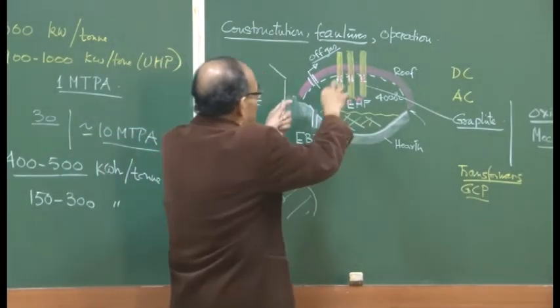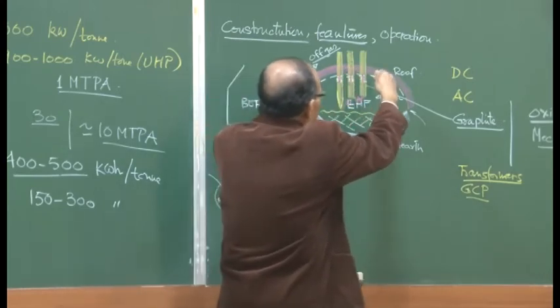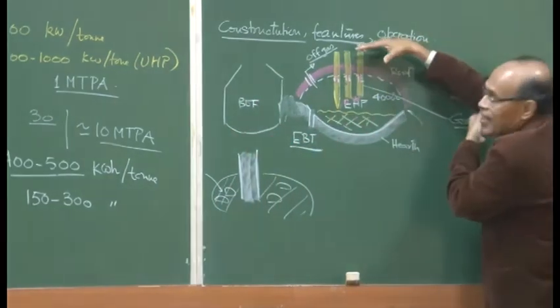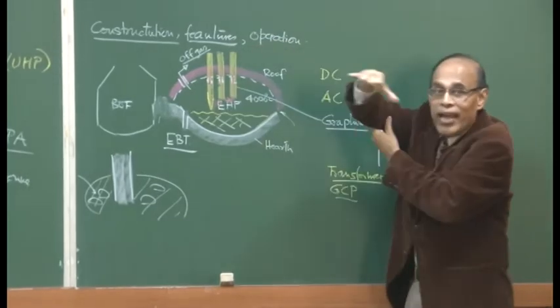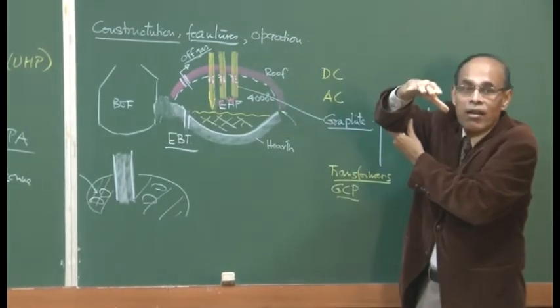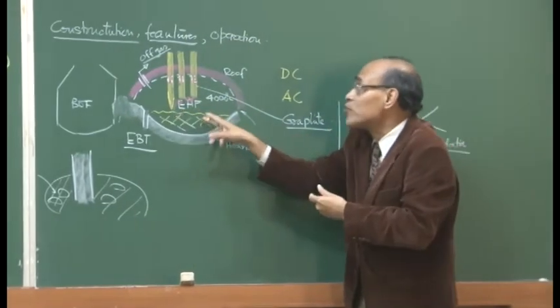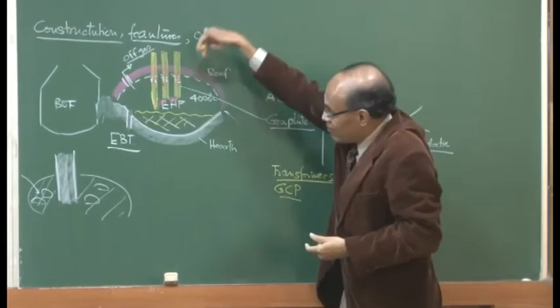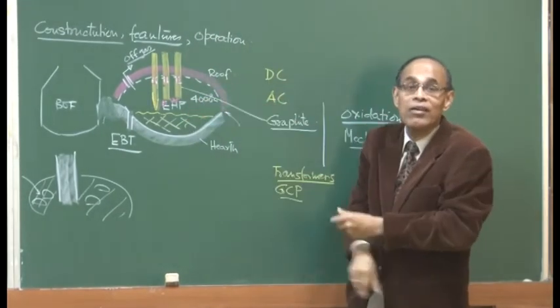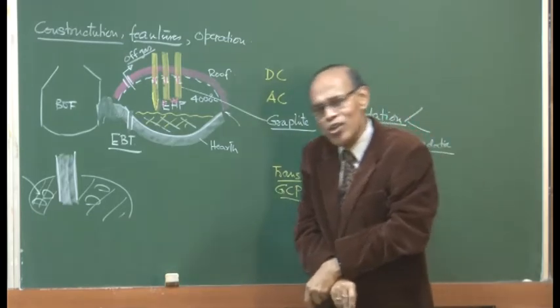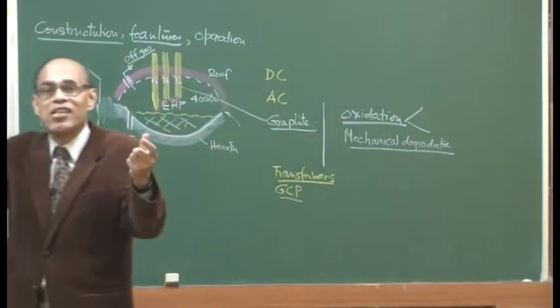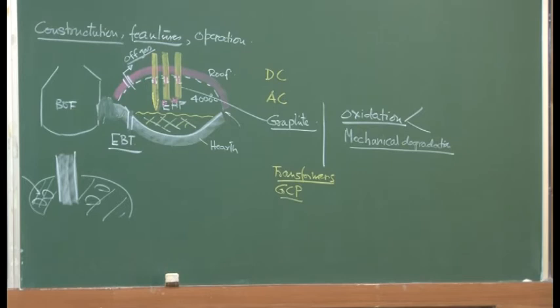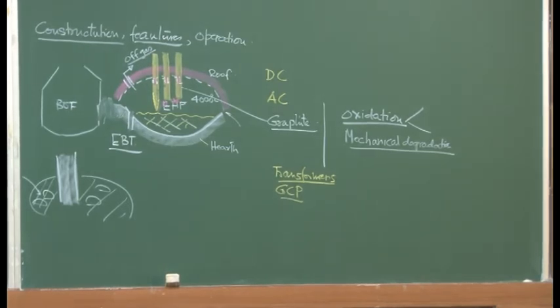we have scrap, these electrodes are attached to the roof. So the robotic arm which is placed like this can swing and then take the entire electrode attached to the roof, exposing the top surface, and then from the overhead crane you can charge the scrap into the furnace itself. And there are also buckets in which scraps are used. So the heavy scraps are at the top and lighter scraps are at the bottom, so that when melting starts, you get some kind of a recirculation.